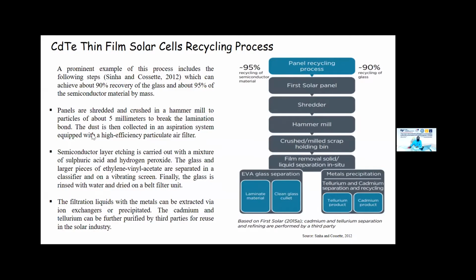We can see the prominent example of this process includes the following steps. Some researchers showed their opinion that it is possible to recover 90% of the glass and about 95% of semiconductor materials. Panels are shredded and crushed in a hammer mill. For the mechanical separation, they use the hammer mill to mill the solar semiconductor materials to about 5 millimeter size, to break the lamination bond. When they break and separate from the EVA layer, the dust is then collected by an aspiration system equipped with a high efficiency particulate air filter.